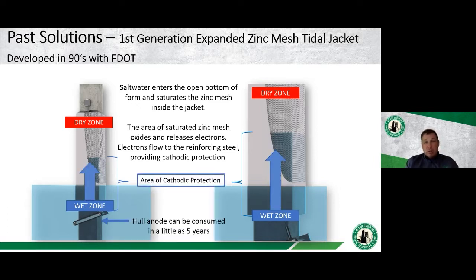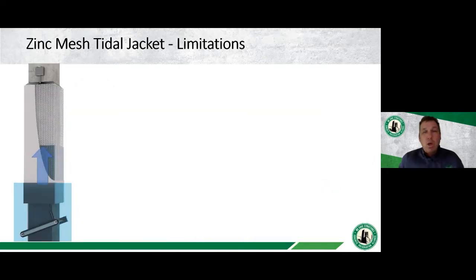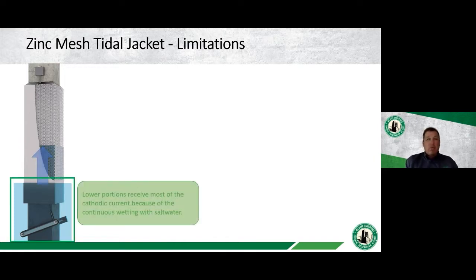So we have our area of cathodic protection. Any of the area within that tidal zone, we're getting some galvanic current in there. Again, like I mentioned previously, we have our bulk hull anode that's attached to the underside of our pile here. One thing to note, from a number of different installations, is the bulk anode can be consumed sometimes in as little as 5 years. So why is the bulk anode being consumed in 5 years? And why are there some limitations on this first generation jacket?